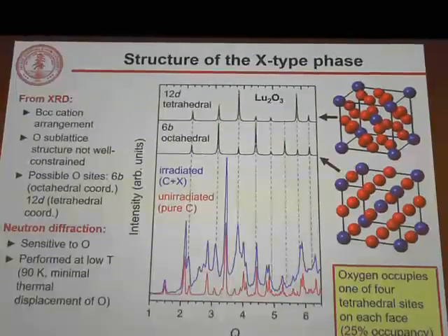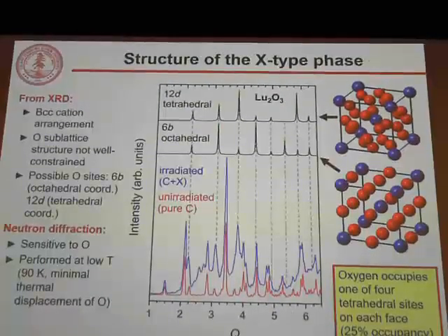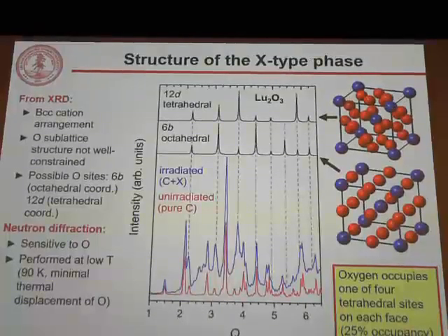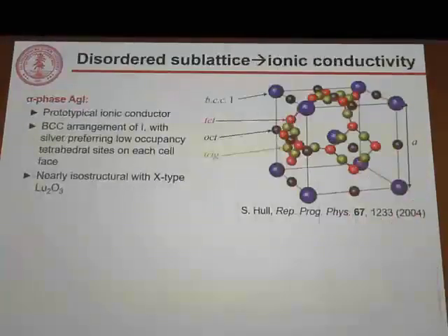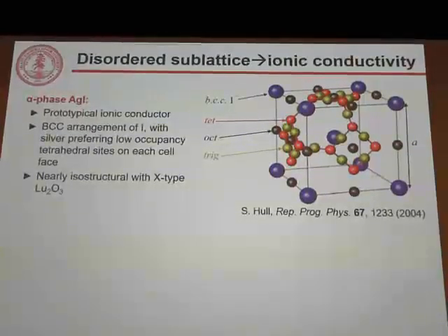And we see, really interestingly, that in this structure, oxygen occupies one of 4 sites on each cell face, giving it a 25% site occupancy, meaning it's very highly disordered. This is unusual and interesting, particularly if we compare it to another material, alpha phase silver iodide. Now, this is the material that ionic conductivity of a solid at relatively low temperatures was first observed in. It's the prototypical ionic conductor. It has a body-centered cubic arrangement of iodide, with silver preferring to occupy low occupancy sites, tetrahedral sites on each cell face, making it nearly isostructural with lutetium sesquioxide.